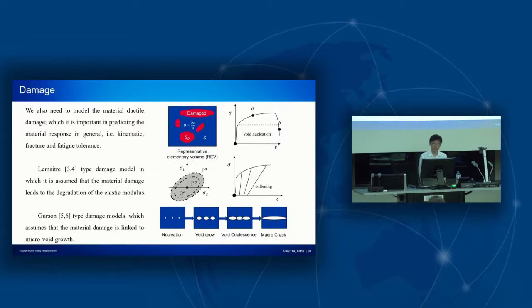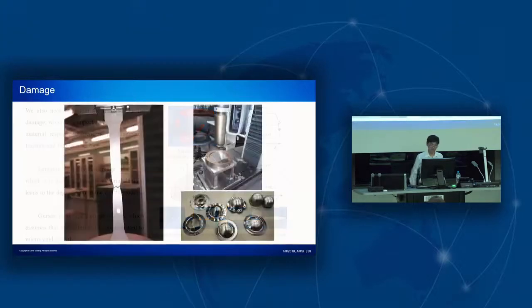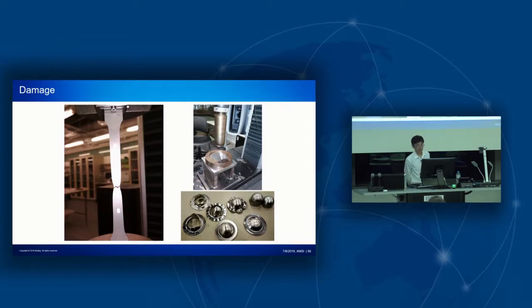And both of these ductile damage models will result in a softening behavior in the material, which can be represented as a shrinking of the yield surface. And this damage model can be calibrated by comparing the crack initiation from experiment data to the predicted crack initiation in the simulation.